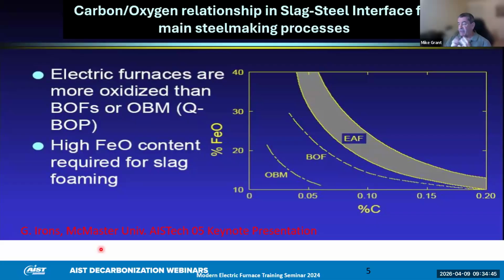So we can't escape the fact that steel is an iron-carbon alloy, and so carbon is going to play a role in this picture no matter what. If we look at the three main processes for producing steel, the electric arc furnace, the BOF, and the bottom blown OBM, these show that as we blow our carbon down, say to a low carbon content of 0.05 carbon, we are oxidizing quite a bit of our raw material, our scrap, our metallic iron. And you can see a typical 0.05 carbon tap heat can put about 40% FeO in